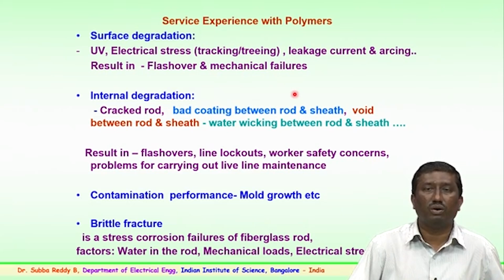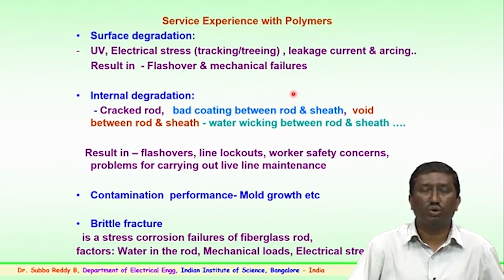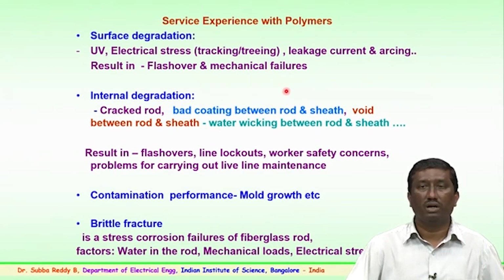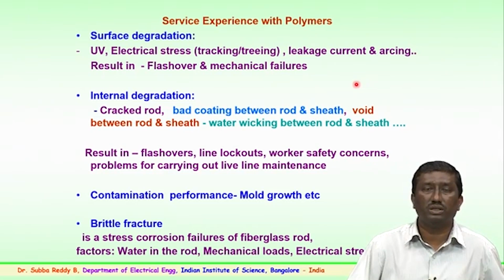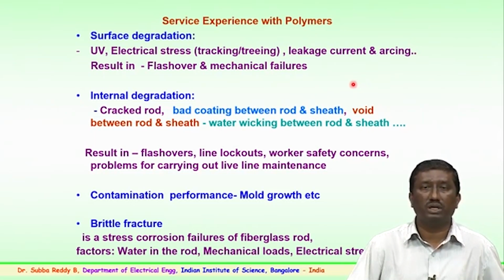So, this tracking or treeing of the surface could happen over a period of time because of the electrical stress, wherein the leakage current and small arcings, known as partial arcing or scintillations, could happen, which could result in flashover and sometimes mechanical failures because of the surface degradation.